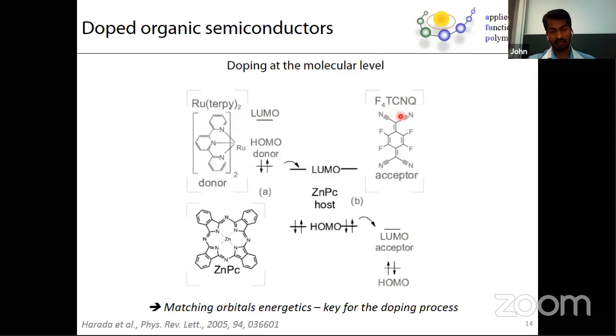On the other hand, one of the famous dopant systems is F4TCNQ, which is very highly electronegative in nature. It has a very low lying LUMO, quite lower compared to many other organic systems, even lower than the HOMO of the zinc phthalocyanine. When you take zinc phthalocyanine and F4TCNQ in a cuvette or in a beaker and just add a solvent and mix them together, an electron would transfer from the HOMO of the zinc phthalocyanine to the F4TCNQ LUMO. So with F4TCNQ you p-dope, and with ruthenium bisterpyridine you n-dope your zinc phthalocyanine.